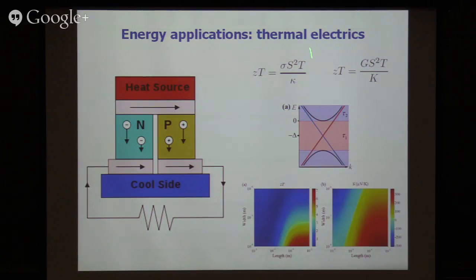Its efficiency can be conventionally expressed by a dimensionless quantity called the ZT figure of merit, which involves the electrical conductivity, the Seebeck coefficient, and the thermal conductivity. The reason we cannot increase it is that there are intrinsic relationships between them. For example, a very famous one is called the Wiedemann-Franz law, which governs the relationship between electrical conductivity and thermal conductivity. This is a formula almost everyone writes down.